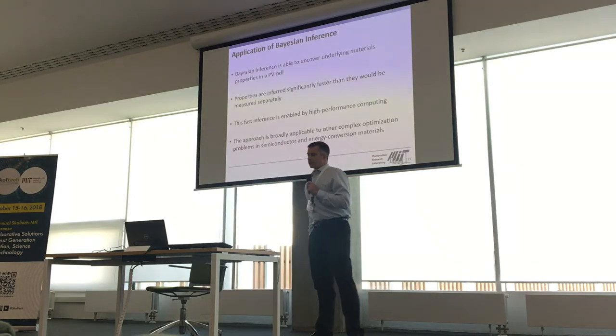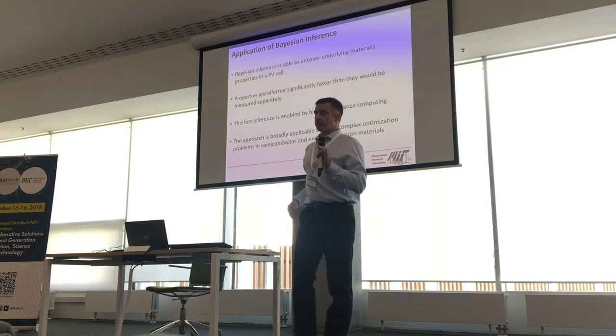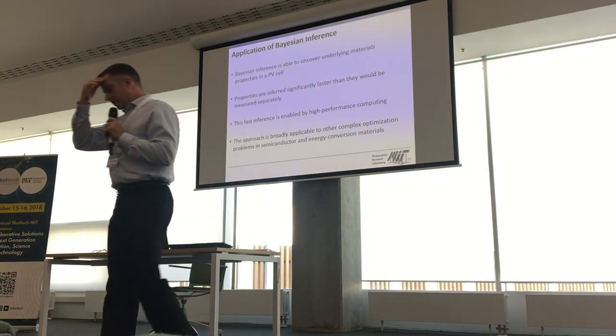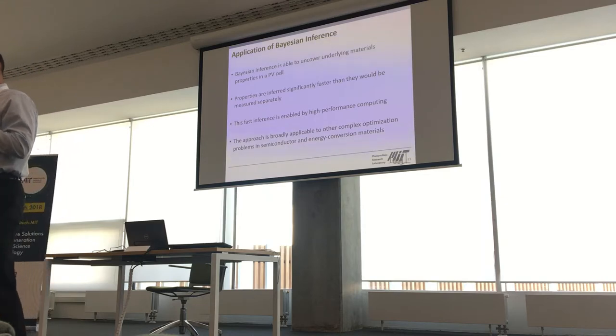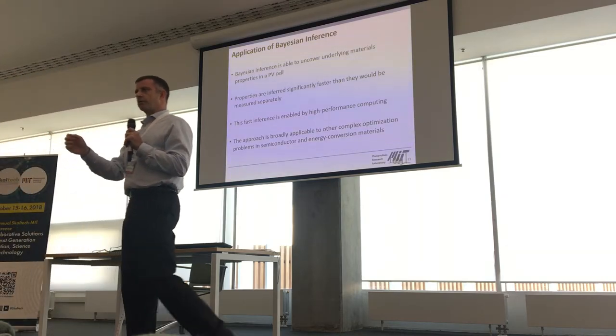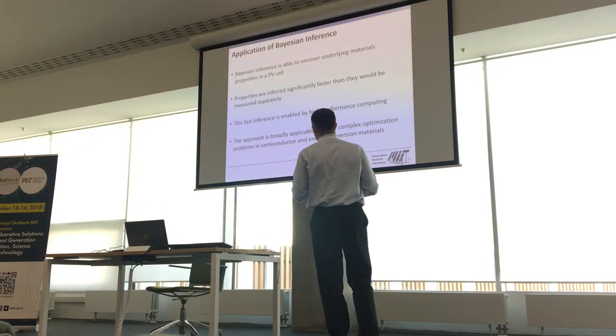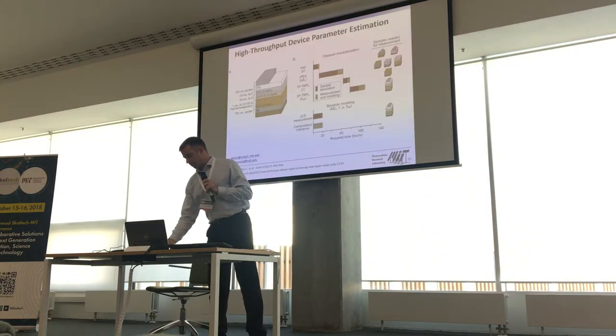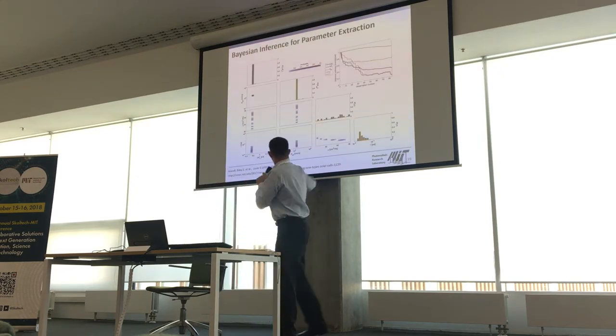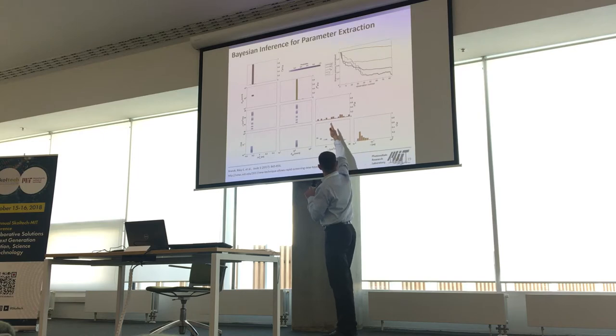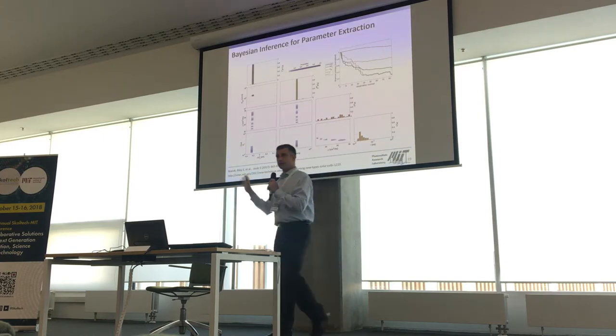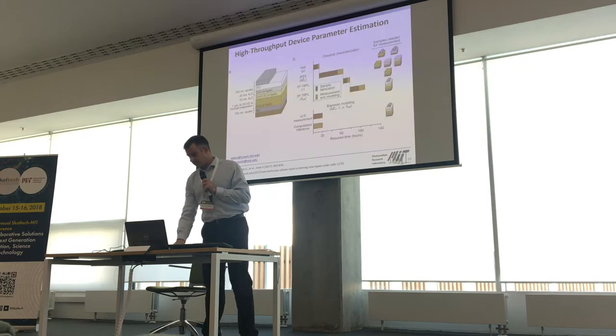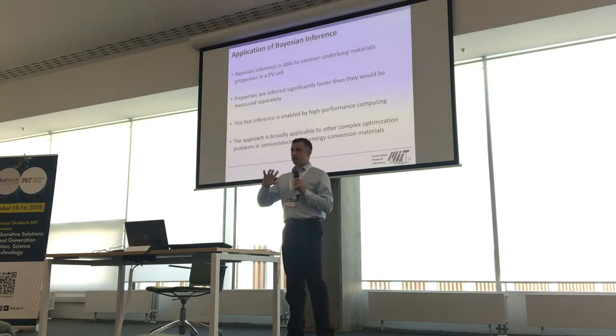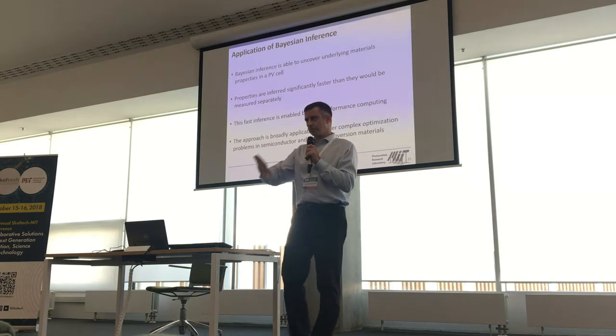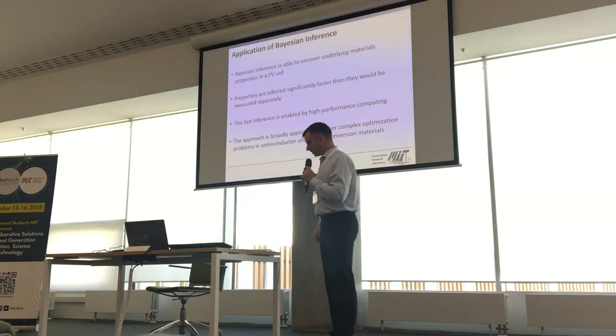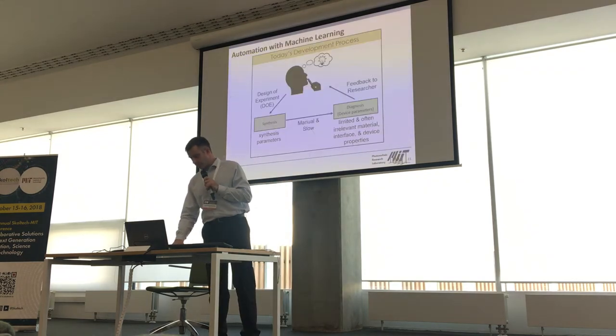The big advantages of Bayesian inference over, say, a multivariate fitting, why not just use multivariable fitting? Multivariable fitting does not take the probability distribution functions into account. In other words, it provides you a number and some error, perhaps. Number two, the correlations between variables are not ascertained. So, for example, here, you can see very clearly the mu tau product, the current voltage product effect here. And number three, a Bayesian inference wrapper allows you to separate out measurement uncertainty from model uncertainty, what we call aleatoric and epistemic, or stochastic, error.